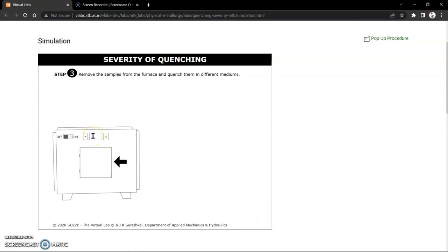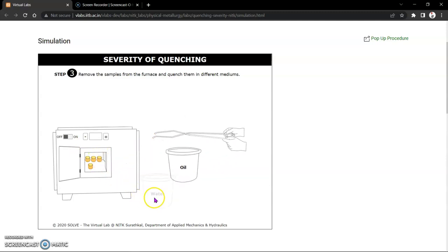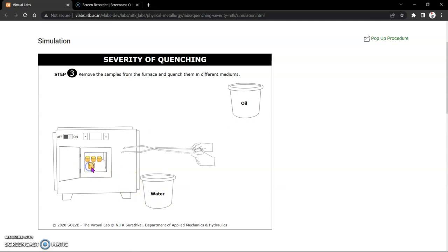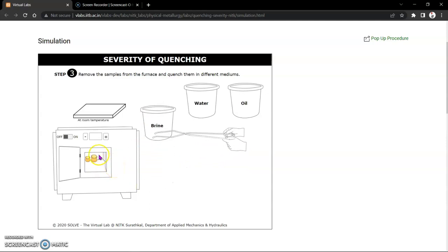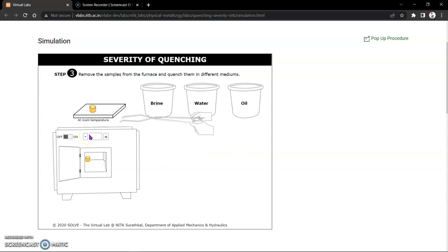Then, step 3, remove the samples from the furnace and quench them in different mediums. First, open the door of the furnace and put one sample in oil medium. After that, in water medium, then brine medium, and one sample at room temperature. Then the last sample we let cool in the furnace till 400 degrees.